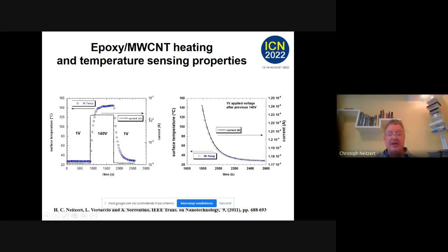That is now what you can do with the epoxy. Here we heat it. We apply 1 volt, it's constant. Then we apply 140 volt, and we get 140 degrees by chance. It's the same 1-to-1 relation. Then we apply again 1 volt, and we measure the resistivity, and we see the cooling transient.